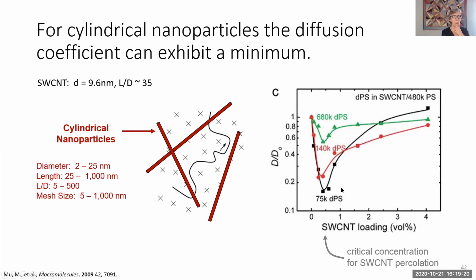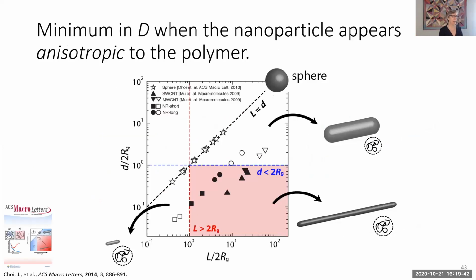And this was really puzzling because this minimum corresponded to the critical concentration where we got electrical percolation. So that means we had a percolated network. And so time went by, and then Russ Composite had a fabulous postdoc, Ji-Hoon Choi, who made nanorods with different lengths. I mean, the nanotube experiments are inherently complex because you don't have good control over the length or the diameter. So Ji-Hoon synthesized these nanorods, and we found that there was a particular condition that had to be met for the diffusion to go through this minimum.